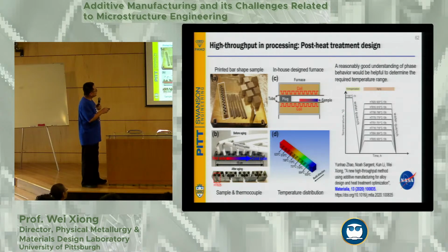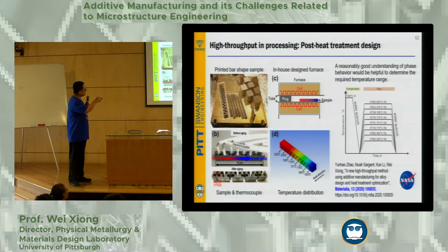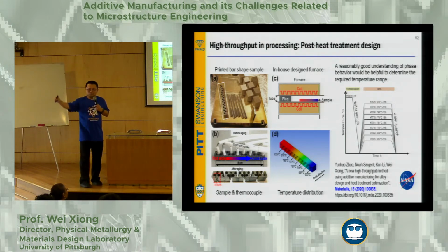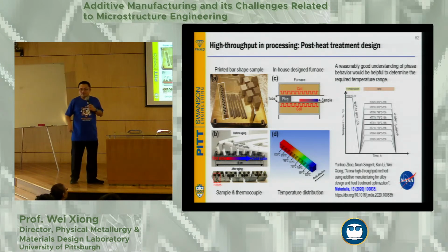So this is the kind of tube furnace, all right? So we just keep this plug, okay? Close this part. And then we actually can do a printing with 3D printing. So we can print a long bar shape sample with this laser powder bed fusion process. And I put this long bar shape sample to here, okay? I heat it up, and then suddenly I can introduce a gradient temperature zone, okay?